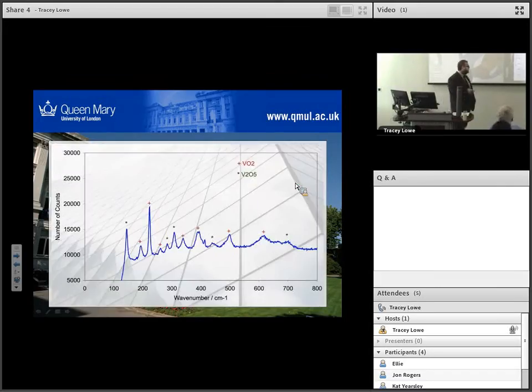Looking at some Raman, we can see we've got some vanadium dioxide present, which is good. We've also got some V2O5. This is pretty normal for vanadium dioxide - vanadium 4+ is not a very stable ion, and it will oxidize readily.